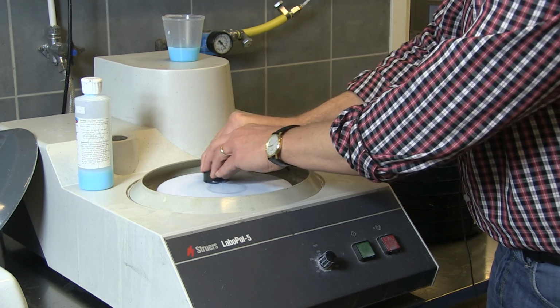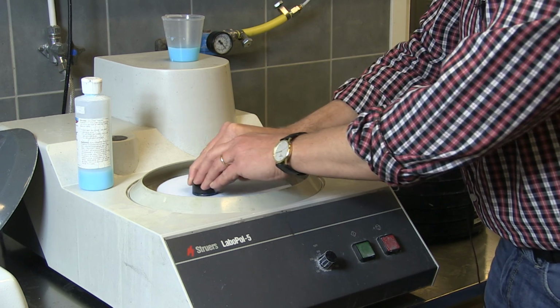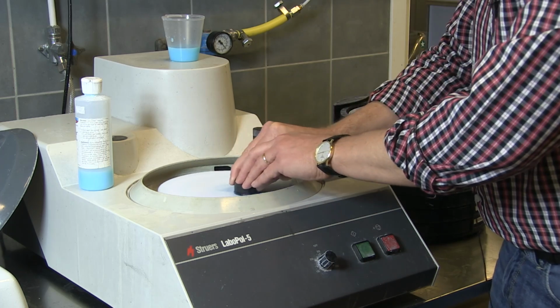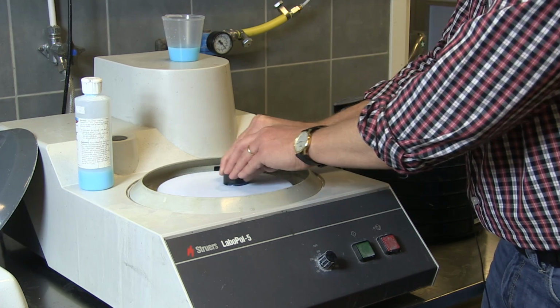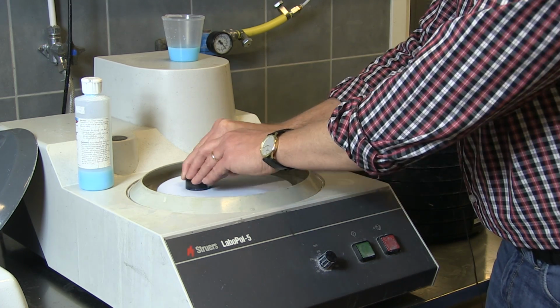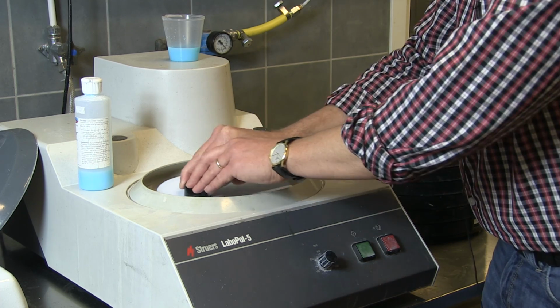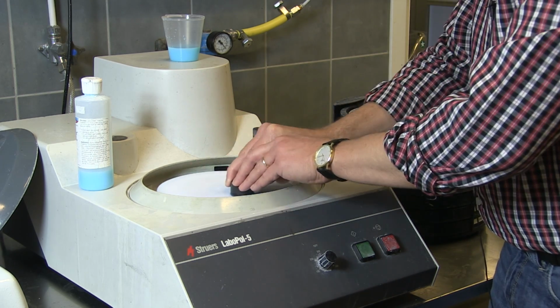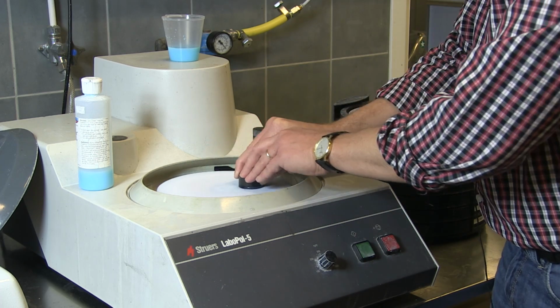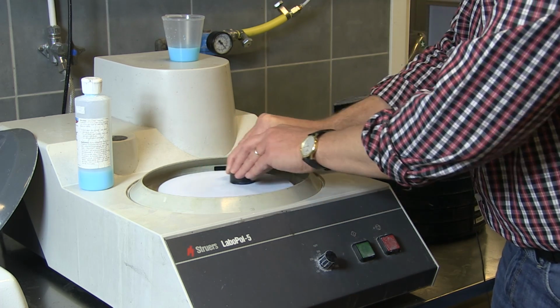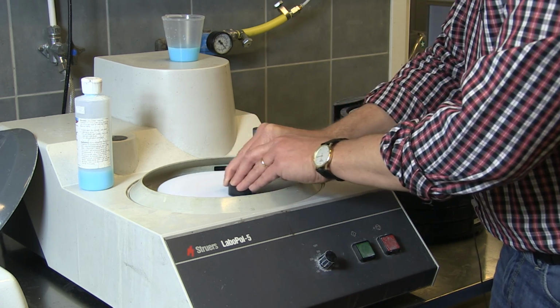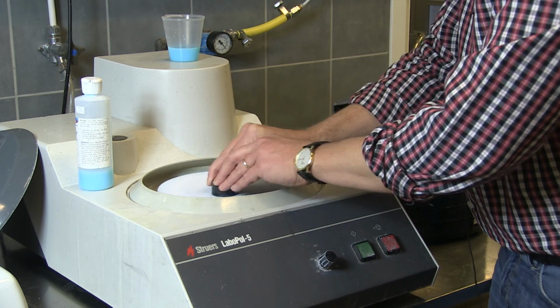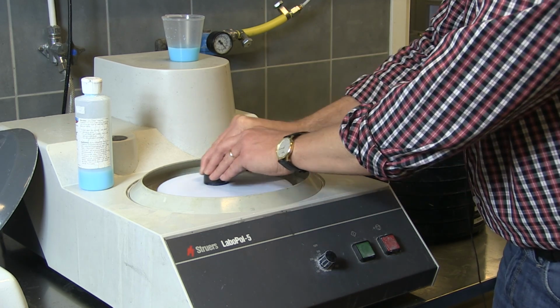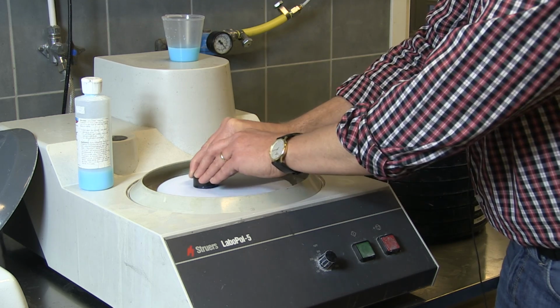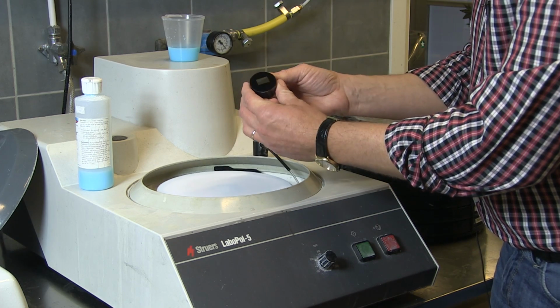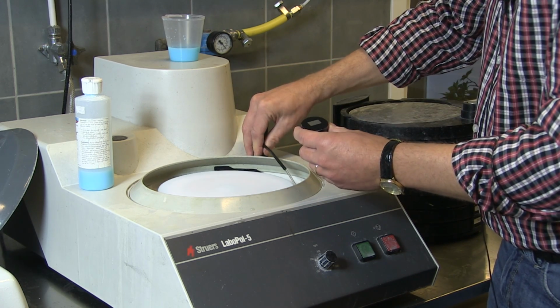And I keep polishing. And I would like to give you an advice here, and that is that you should not over polish on a napped cloth like this one. 1 to 2 minutes on a steel sample, not more. There are exceptions for longer polishing time, but for manual polishing, 1 to 2 minutes on a napped cloth. So I'm satisfied there, as a matter of fact.